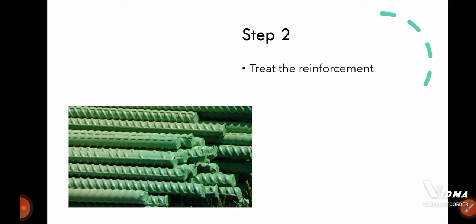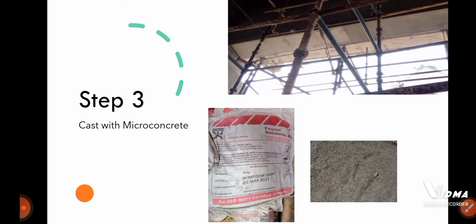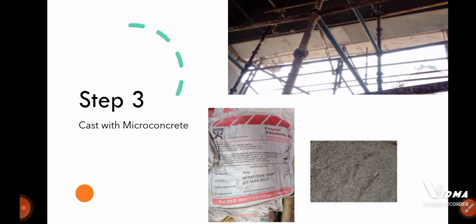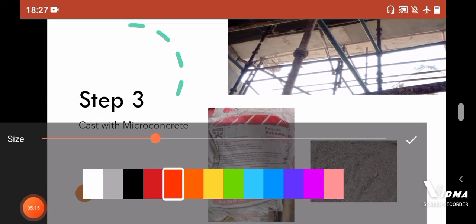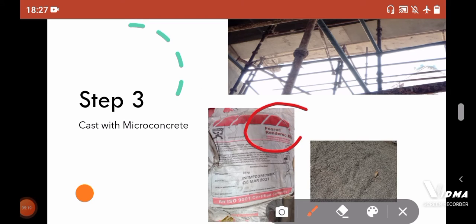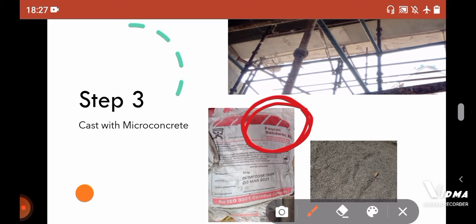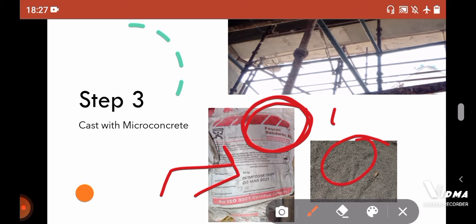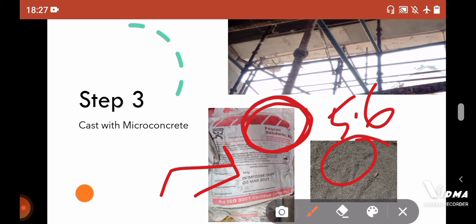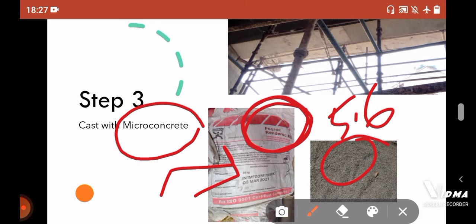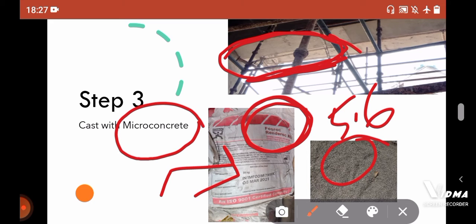Now it's time to move forward to step three. Your reinforcement is ready and at the bottom of the girder there is no concrete, so what you have to do is put new fresh concrete. But this concrete is quite different compared to your normal concrete. Here I am using micro concrete and this micro concrete is from Fosroc - you may be familiar with Fosroc or BASF if you are associated with this type of rehabilitation job. Fosroc is very familiar to this rehabilitation world. In this micro concrete pack you need to add some coarse aggregate, the size is normally 5.6 mm. With the addition of this 5.6 mm aggregate you are preparing your micro concrete. After application of micro concrete, the girder bottom looks like this one. Here you can see that this is a freshly prepared soffit of your girder after the application of your micro concrete.